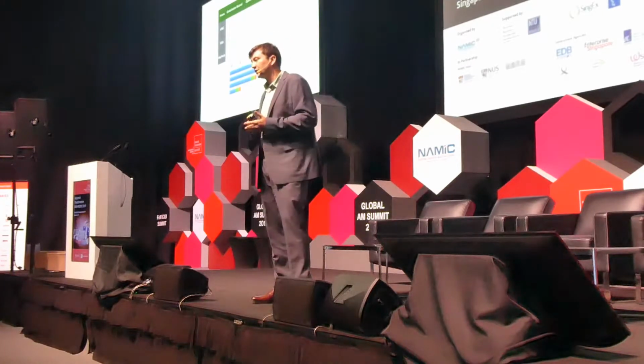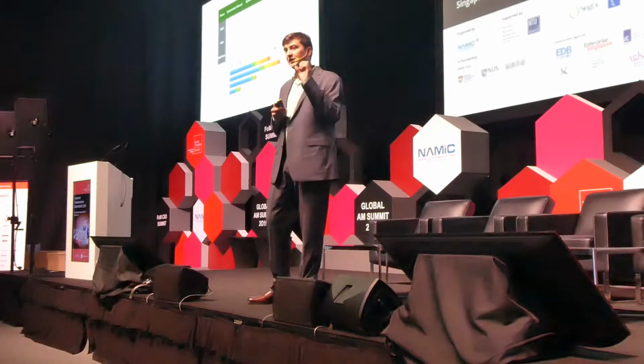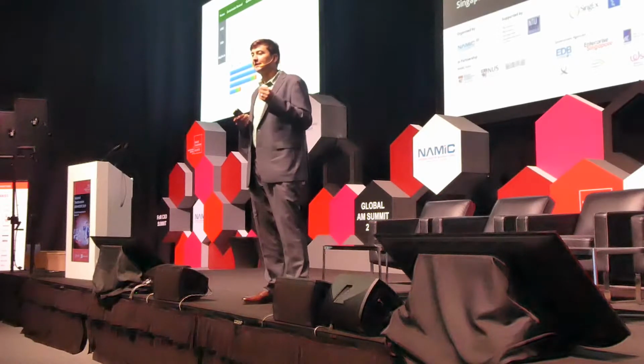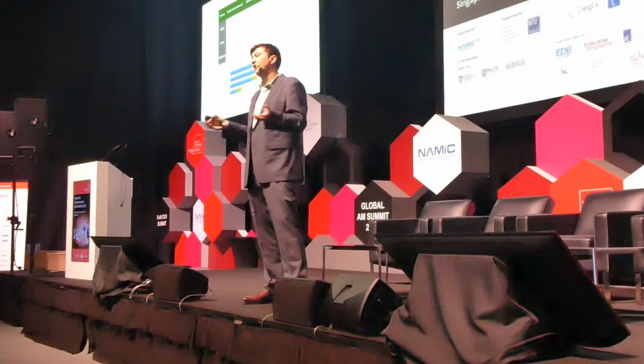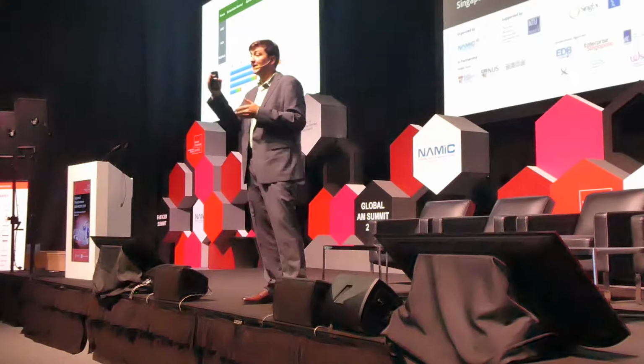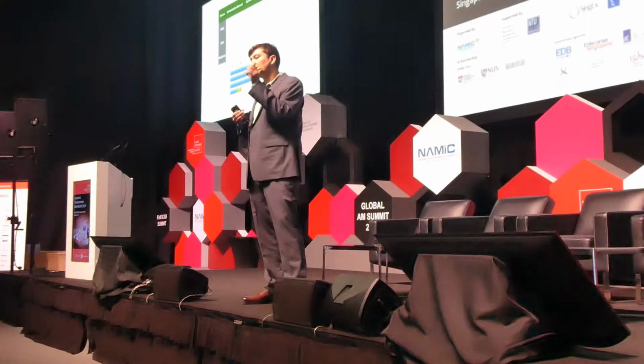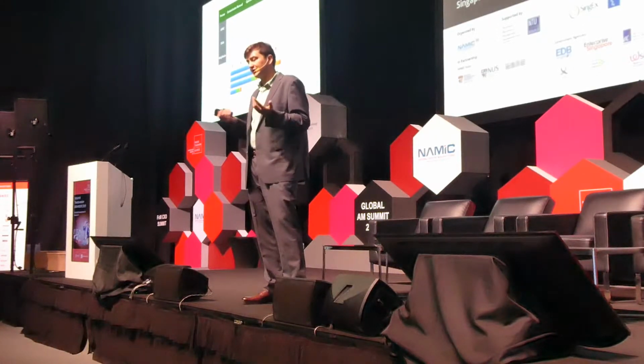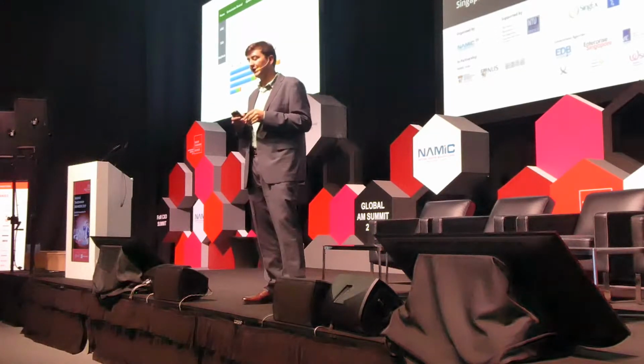Then you have EIGA, which is Electrode Induction Gas Atomization, and this process requires a small diameter ingot, like 2-inch diameter, and then you basically put an induction coil around it, and you drip melt it into an atomization die. The process is really energy intensive because it takes a lot of energy to make that ingot, but it also takes a lot of energy to get that ingot hot enough to drip into a point where you can do the atomization. It's also rather inefficient gas-wise, so gas consumption of an EIGA is very high.